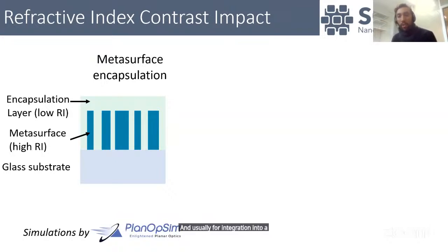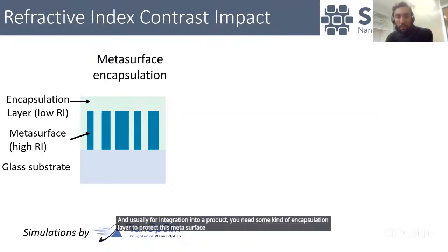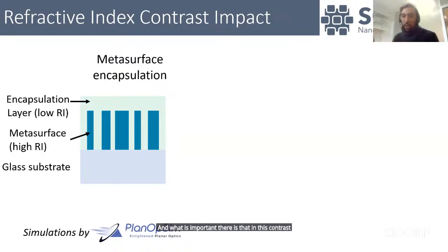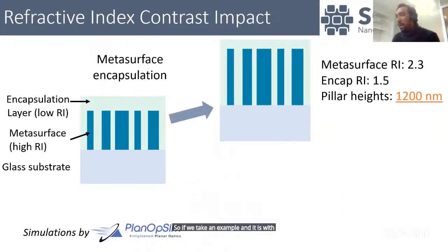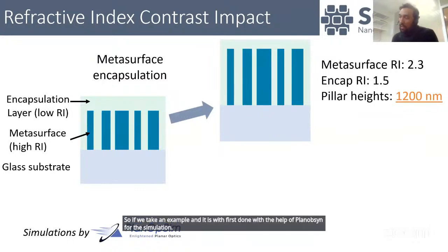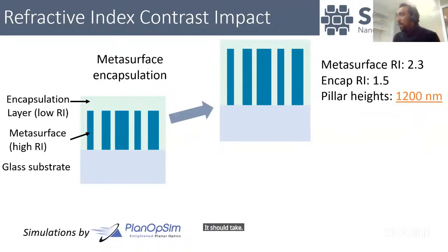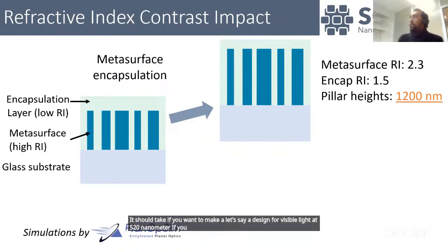And usually for integration into a product, you need some kind of encapsulation layer to protect this metasurface from mechanical damages and to have better integration into your product. What is important there is the refractive index contrast of this encapsulation layer with the metasurface. If we take an example, done with the help of PlanOpSim for the simulation: if you want to make a design for visible light at 520 nanometer, if you use a material with a refractive index of 2.3 and an encapsulation layer of 1.5, you end up having to etch pillars with a height of 1.2 micron.